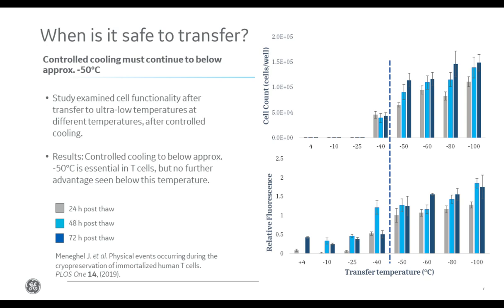-80 degrees seems to have been chosen as historically, when mechanical freezers were first introduced, the -80 value was chosen to match the temperature of dry ice, which has commonly been used as a coolant. Passive coolers started to be used in these -80 degree freezers, which gave a natural endpoint of -80 degrees and which carried over to controlled rate freezers. The extracellular glass transition temperature around -120 degrees also had very little evidence. Certainly, cells must be stored long-term below this temperature, but cells would long have ceased dehydrating, and the results from transfer from -80 degrees don't appear any worse than those from -120 degrees. So to solve this, we carried out an experimental study where we cooled immortalized T cells in a controlled manner to several endpoint temperatures, ranging from plus 4 degrees down to -100 degrees.